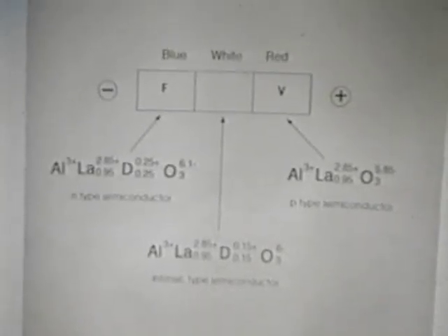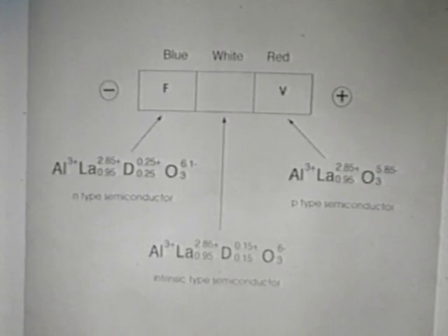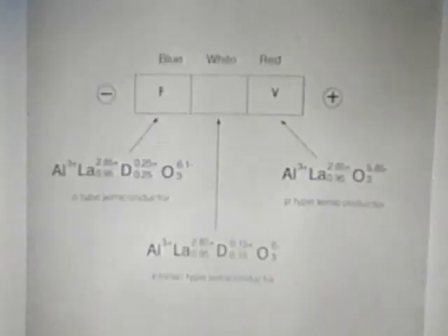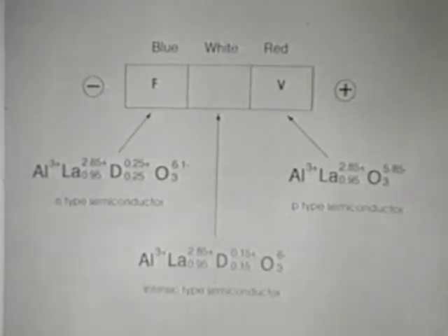Anyway, so in the negative region, the deuterium are attracted by the cathode, and you have an extra density of deuterium in that area. I'll give you the blue color. I have to tell you that this crystal, when it is intrinsic, is white. When it has vacancies, it becomes red due to the vacancies. So I don't have samples with me, but they're just red anyway. So if you load it with deuterium by putting it into the furnace with deuterium in it, it turns out white because the vacancies have been filled with deuterium.